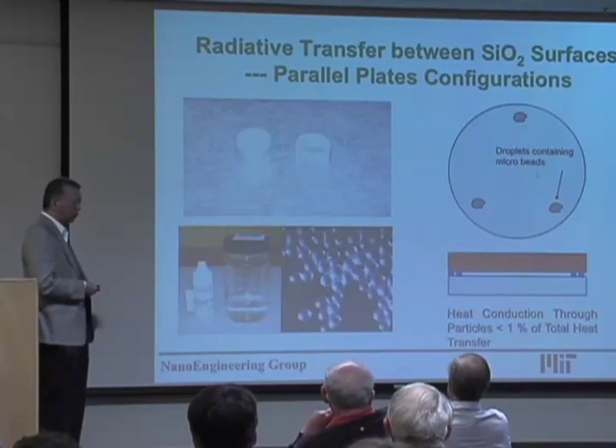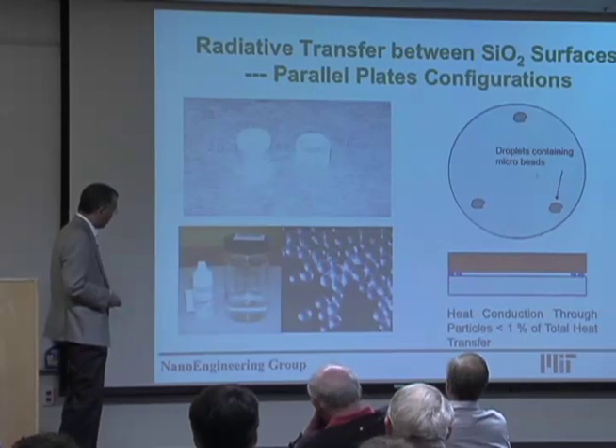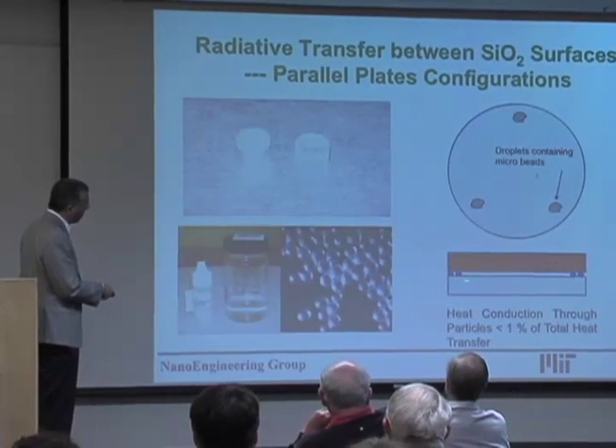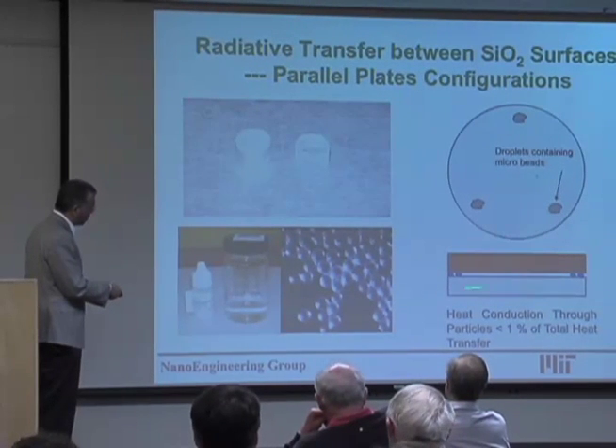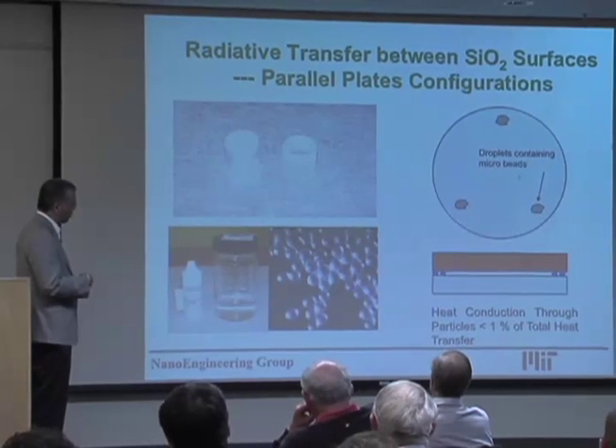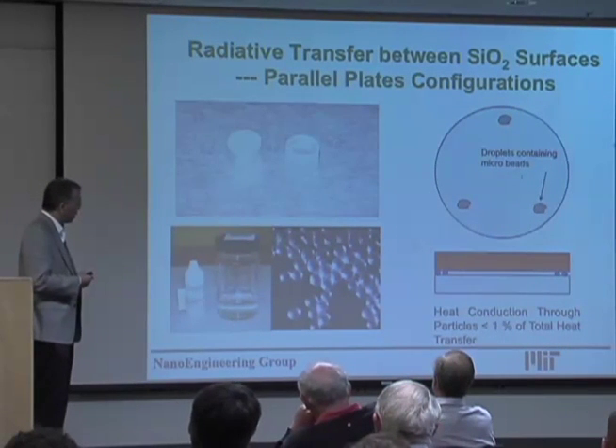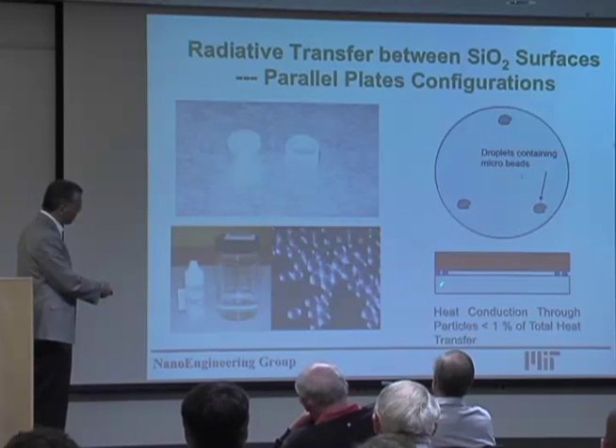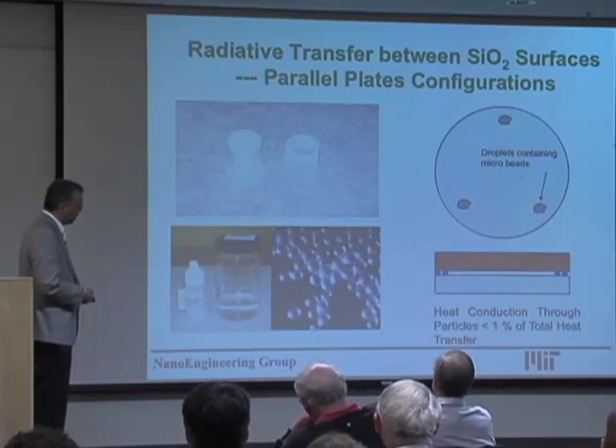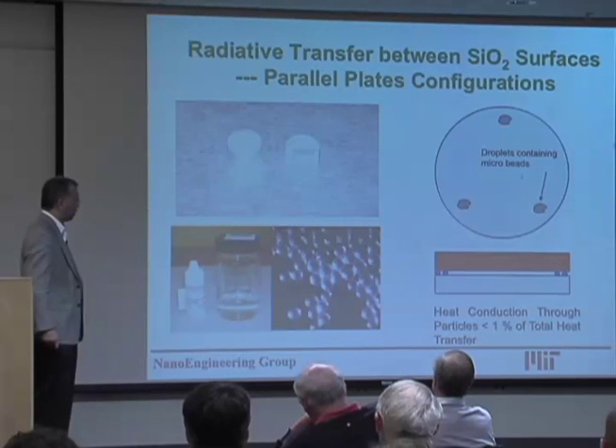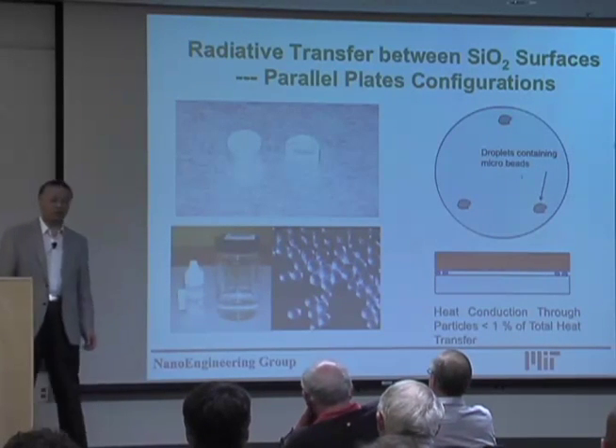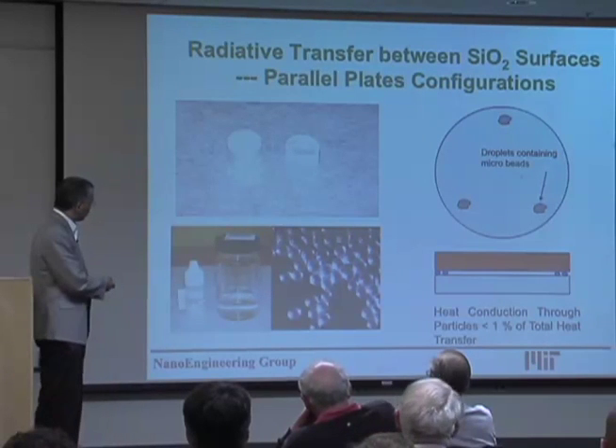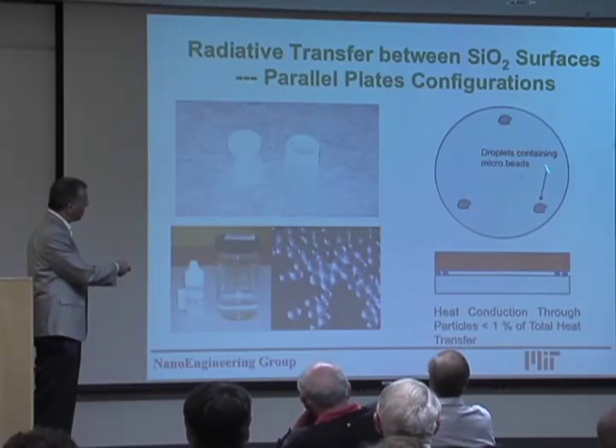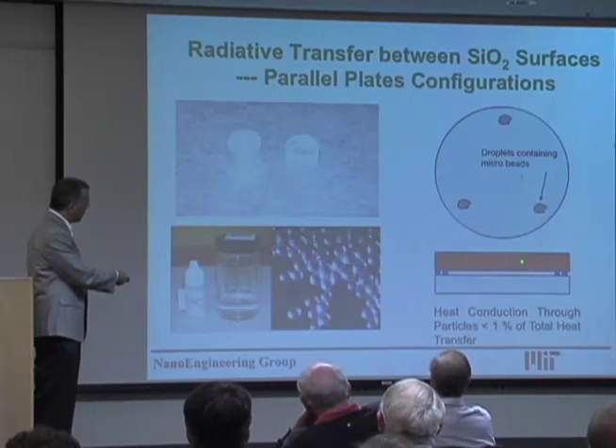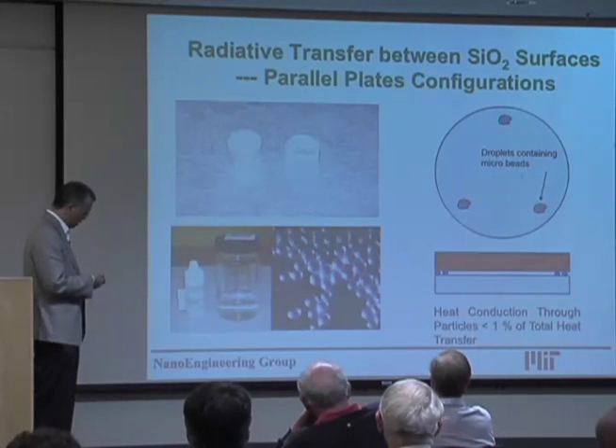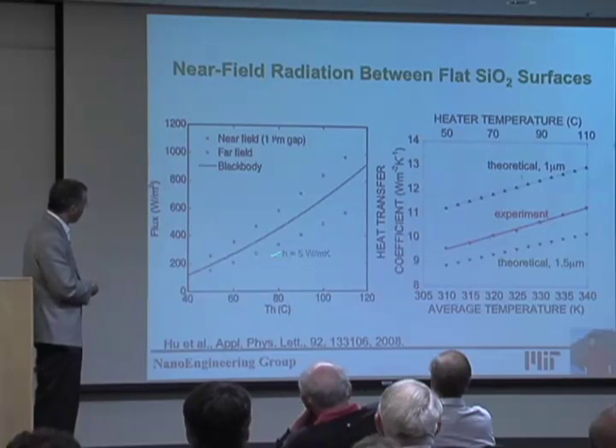How we did it is we used polymer spheres as a spacer between the hot and cold plates. Because the polymer sphere has a very small radius and a low thermal conductivity K, the heat leakage through the spheres is small. Our calculation shows that the conduction heat transfer is less than 1%. So we used basically two quartz plates, heated one side, and measured the heat flux on the other side, and we reported some experiments.